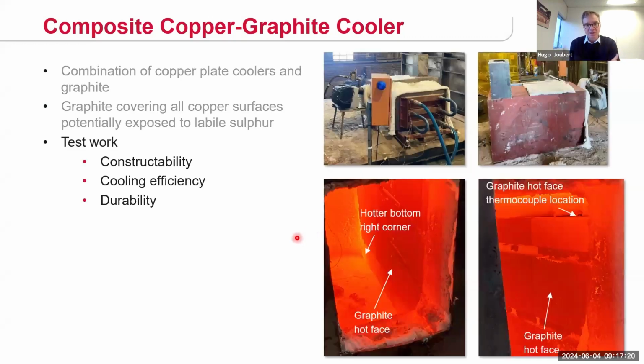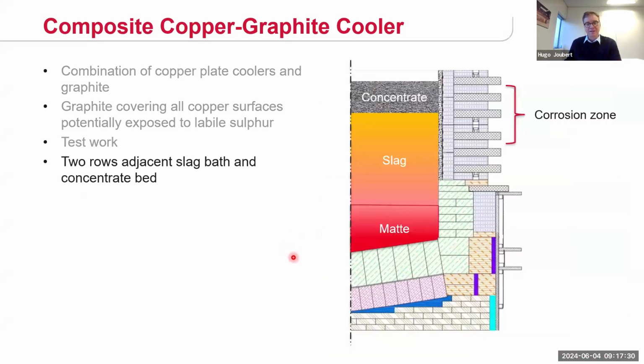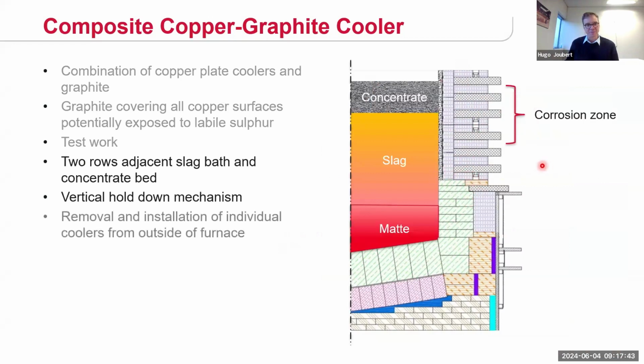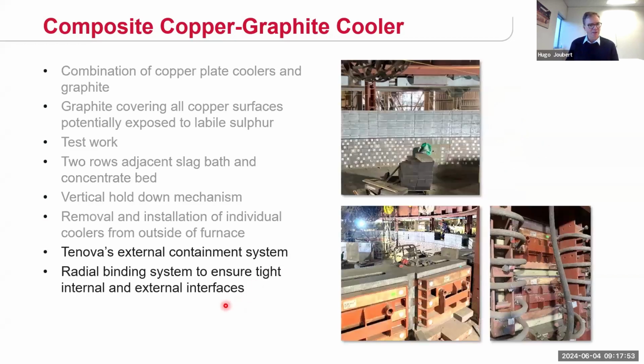We did extensive test work beforehand on this composite cooler to confirm the constructability, the cooling efficiency, as well as the durability. And you can see we're installing 2 rows of these coolers on top of each other. We have a vertical hold-down mechanism to ensure that you don't form horizontal gaps between the coolers, as well as between the bottom coolers and the refractory lining below. The coolers are designed so that you can install individual coolers and remove individual coolers from the outside of the furnace. And we use our external containment system to cover all the interfaces between adjacent coolers, vertical and horizontal, as well as between the bottom cooler row and the refractory lining below.